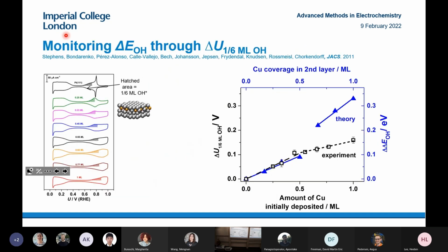So we changed the amount of copper we deposited, and then annealed the platinum single crystal, and we found that we could see a shift in the OH peak in the voltammogram, which corresponded to a shift in the OH binding as a function of the amount of copper initially deposited. This is shown here, and if you look at the black line first, this shows the shift in the CV as a function of the amount of copper. We see more copper, more destabilized OH. However, the theoretical calculations suggested you should see even stronger destabilization, especially when you put a lot of copper in the second surface layer. However, we didn't reach this regime predicted by the theoretical calculations. This was a bit disappointing.